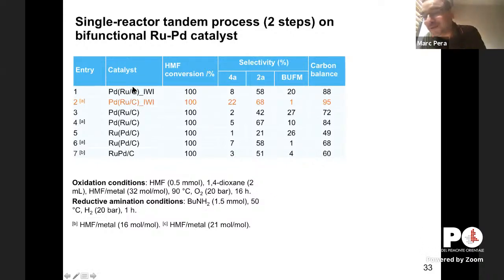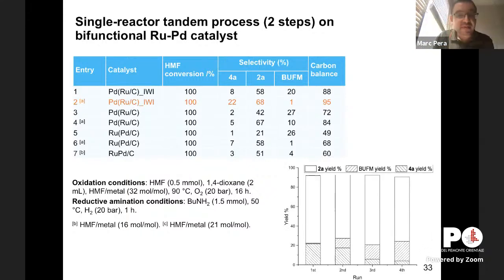We just took the commercial ruthenium carbon catalyst, we impregnated palladium, we tried different protocols, and we found that the best optimized system gives us in a single reactor process 68%. So in this catalyst, you have two bricks, ruthenium and palladium. Ruthenium is working in the first step, palladium is working only in the second step. They are not antagonistic. And you have some recyclability in different cycles. So more or less decent results.